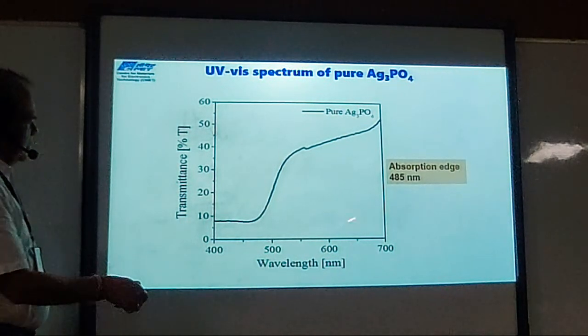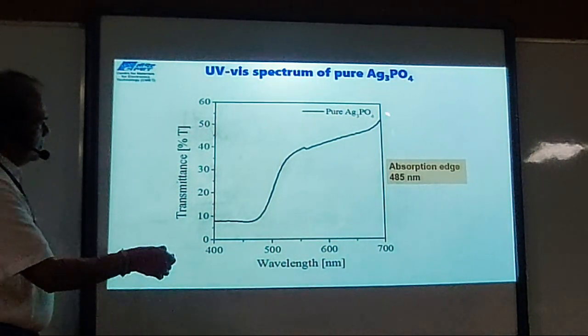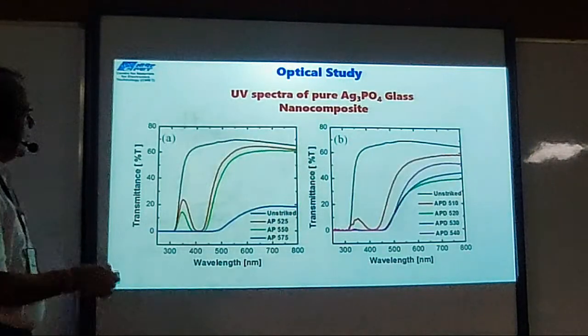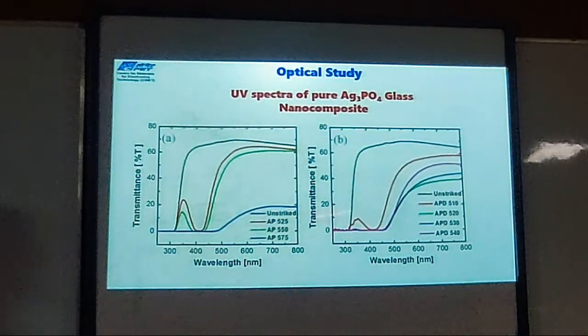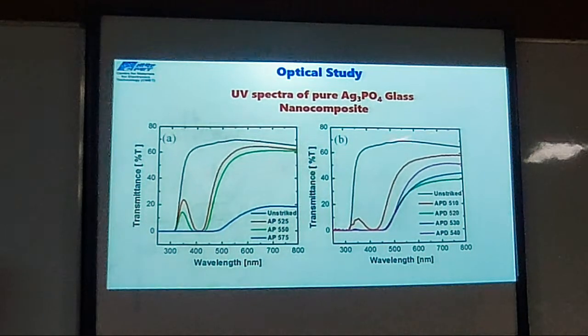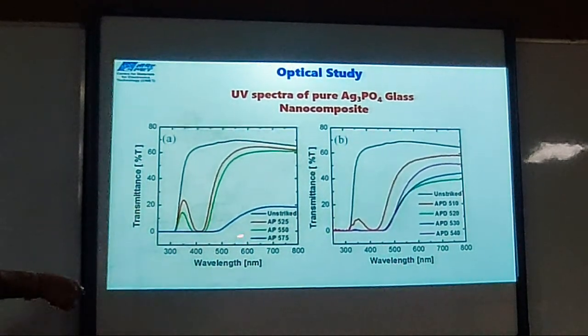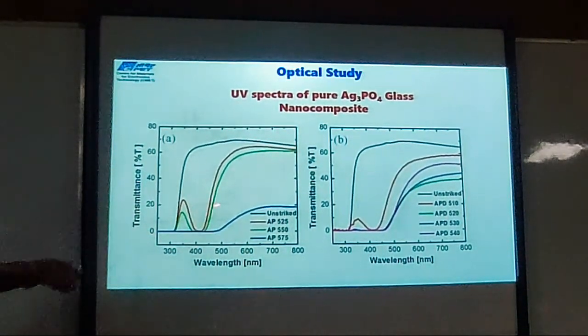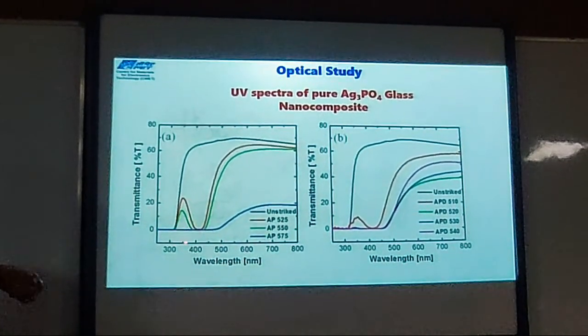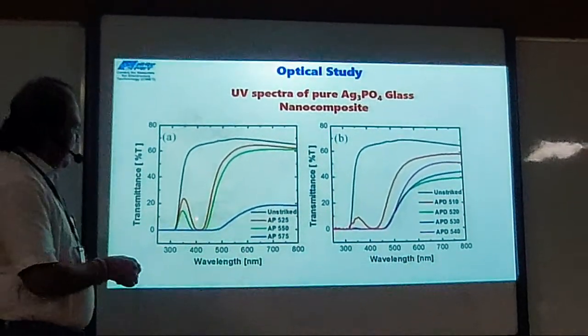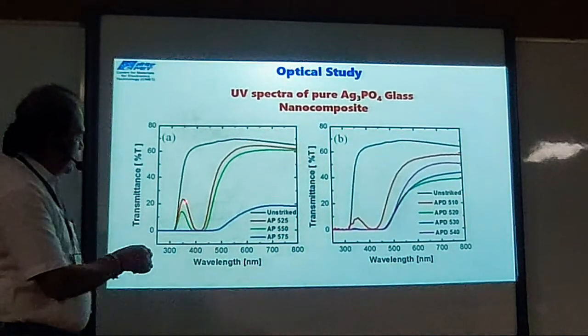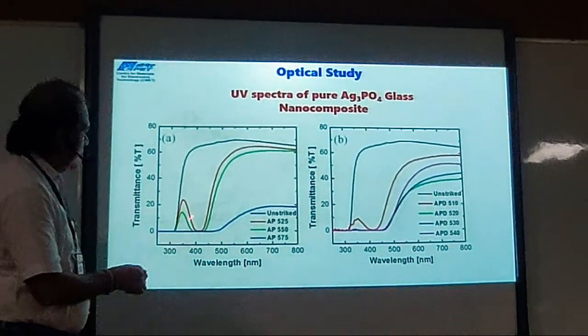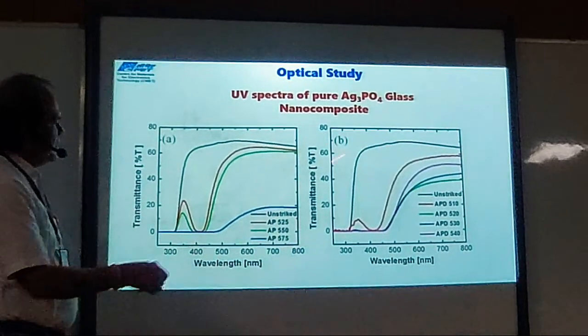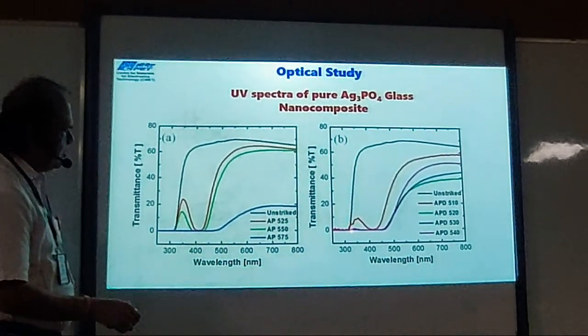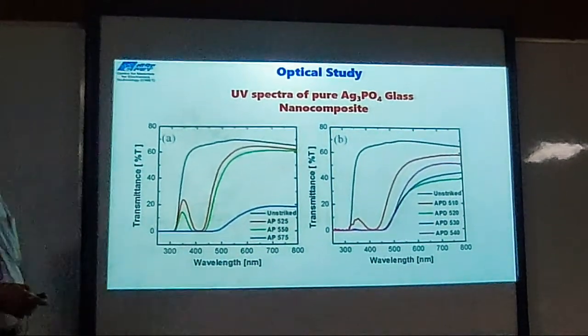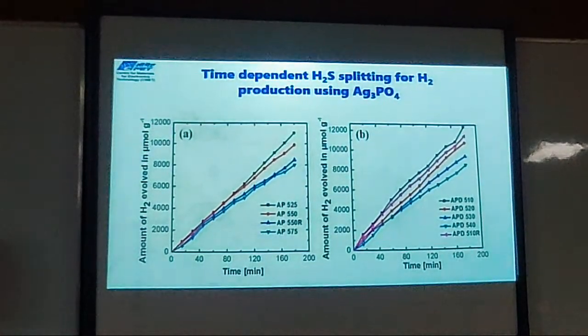So for the visible region, we thought that we can make this powder and immediately put it in glasses and heat treat these glasses, and we get absorption in the visible region. You can see it is the formation of Ag3PO4. Why has this come? What happens during the process? The silver gets decomposed, so we thought whether we can have excess PO4 and suppress this, and we did that. And we get good hydrogen evolution also here.